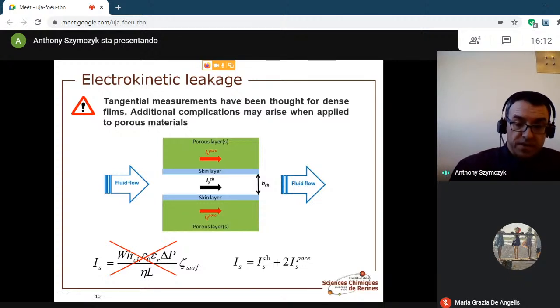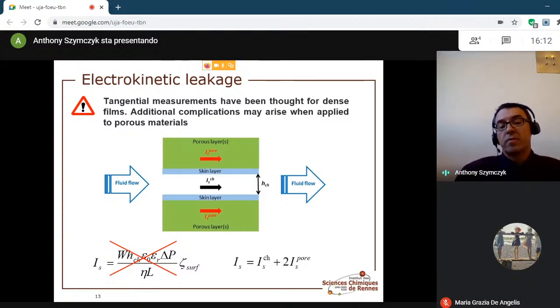However, complications have been pointed out when such tangential electrokinetic measurements are applied to membranes, for which a part of the streaming current is likely to pass through the membrane matrix, and not only on the external surface of the skin layer. From an electrical point of view, this amounts to considering an assembly of resistors in parallel. The total current measurable by the experimental device being distributed in the different branches, namely the streaming channel between the membrane surfaces of the two samples.